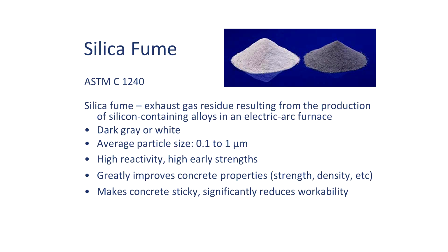You get very high reactivity. But the trade-off is it can make your concrete very sticky if you use it in high quantities. So it's described as having a very high water demand. Again, that very bad habit of using water to change your workability. I've used silica fume in the past. I've blended it. You can blend. The great thing about pozzolans is you can blend them.